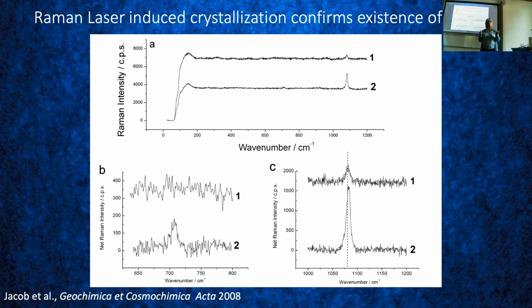And that was quite a surprise, and we were the first to show this. And then the question is, why do you even have amorphous areas in the shell? Because the way we think of crystallization, it's an ion by ion building of a crystal. This is what we're taught at undergraduate level, but this is not what we see here.